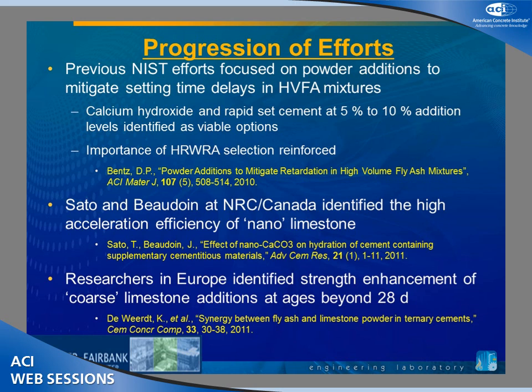About the same time, there was a research group coming out of Europe that was showing that in a lot of the fly ash systems, you got a very nice synergy. When you had even coarser limestone particles in there, you were getting strength enhancement at 28 days and beyond. That was interesting to us because we had used limestone as one of the fillers in the first study that I talked about that we did at NIST.